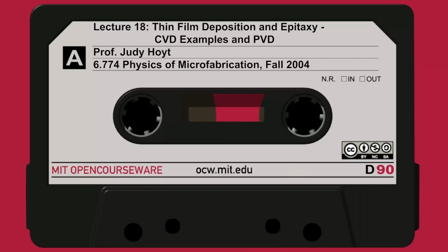Polysilicon is typically put down in a pretty tight temperature range, 575 to 650 degrees centigrade. The morphology of the film and its grain structure, and we'll talk about that in this lecture, depends on the deposition conditions, the temperature and the doping quite a bit. So you adjust your temperature to achieve the type of grain structure that you need for your application.